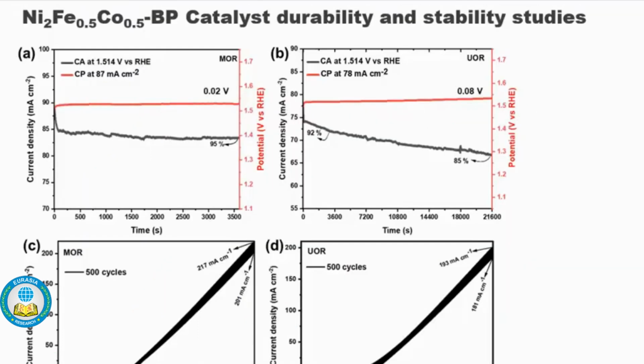The chronoamperometric CA and chronopotentiometric CP tests were conducted to study the durability of the nickel iron cobalt boron phosphide catalyst for both MOR and UOR. Notably, the chronoamperometry profiles depict a fast drop of current density at the beginning of the reaction from 87 to 84, and this is broadly observed in most MOR and UOR studies. For MOR, the catalyst was able to retain about 95.7% of its initial current density after the 1 hour CA test, and conversely, the chronopotentiometry test showed that to maintain a current density of 87 milliamperes for an hour, an additional potential of about 0.02 volts was required.